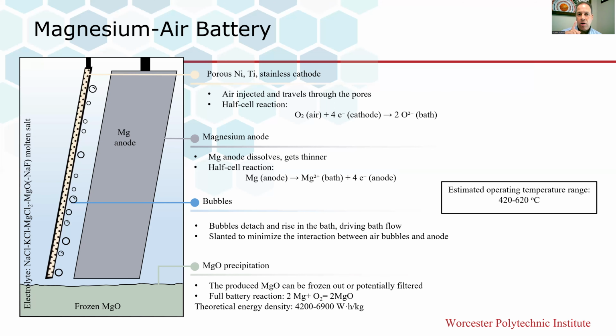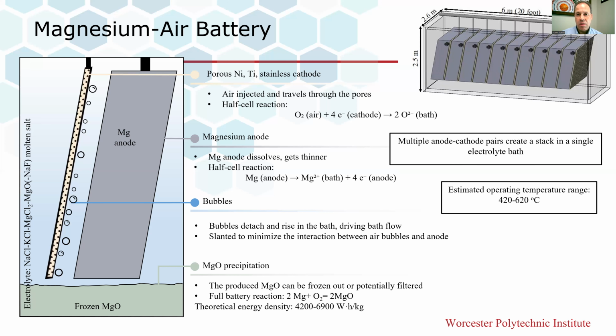which is about 10 times the pack level energy density of lithium-ion batteries. However, we have a very high temperature cell because we have to run with these molten chlorides. Other molten salt electrolytes, such as hydroxides, carbonates, nitrates, etc., will react with the magnesium, forming a magnesium oxide passivation layer. So chlorides eliminate that issue. Based on this, as I said, a shipping container is what we think is the minimum size. This design shows 10 magnesium anodes in a stack, all within a single molten salt electrolyte bath in a 20-foot shipping container. So it's somewhere between 60 and 90 megawatt hours of electricity compared to about 3 megawatt hours that you can deliver from a containerized lithium-ion battery.